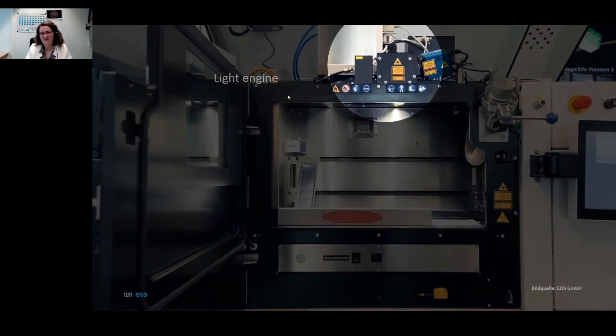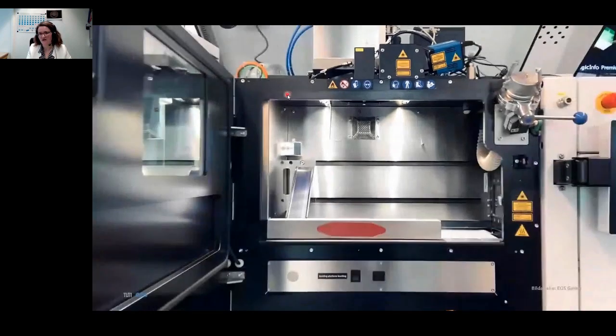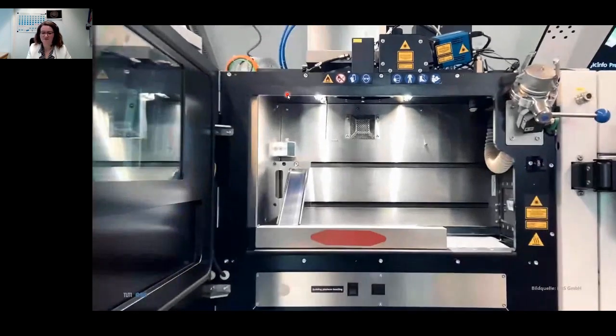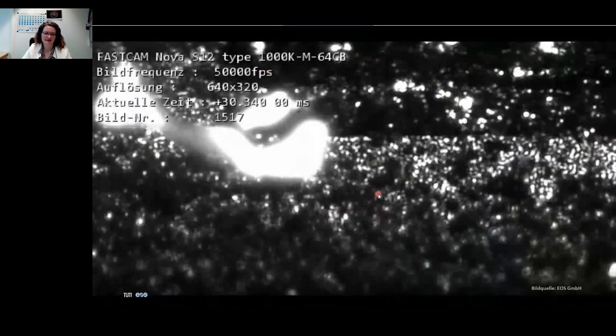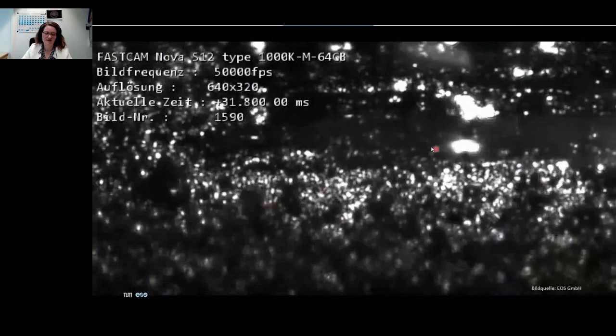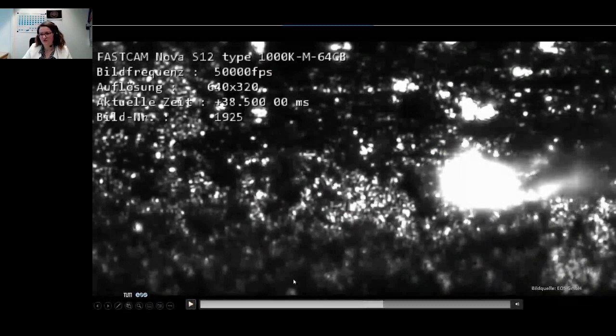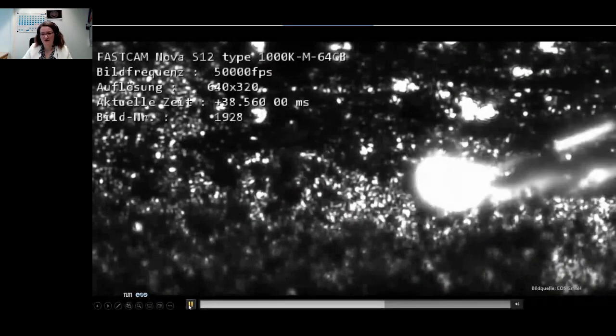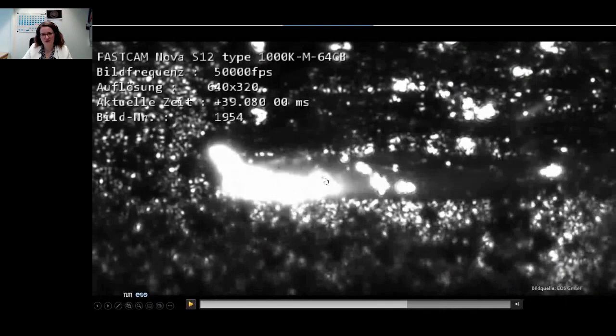If we dive a little bit deeper into, first of all, a conventional, established process in laser-based powder bed fusion, what you can see is a highly dynamic process. The white area is the laser material interaction. So you see this highly dynamic process with the laser material interaction. And what you can also see is a lot of spatter formation. You saw the spatter flying around. It's a highly dynamic process.